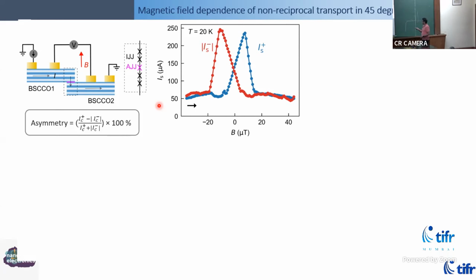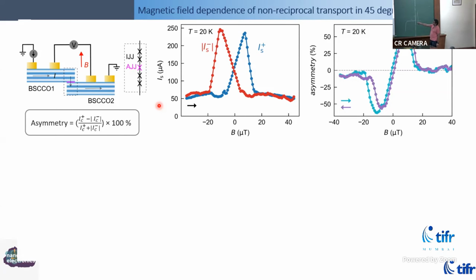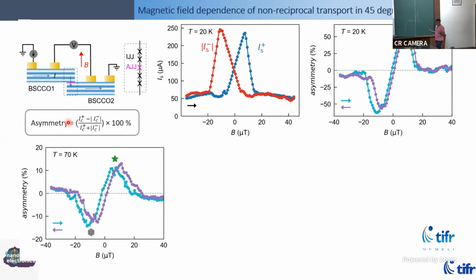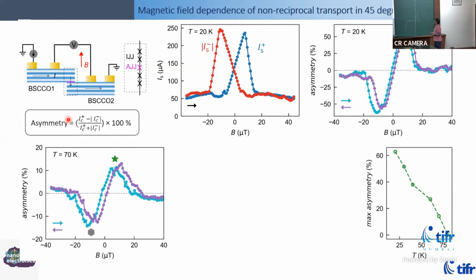So we see that you can get this asymmetry in the switching current. And the way you benchmark the asymmetry, or non-reciprocal response, is this asymmetry parameter, which is the difference. And that difference is actually tunable with magnetic field. That's sort of the interesting physics. And this effect is not one-off. You can measure it at a variety of temperatures, a variety of devices, which we had to measure to demonstrate. Right up to 77 Kelvin, you can see the asymmetry. And this asymmetry at lower temperatures can be as large as about 60%. So the asymmetry decreases with temperature.